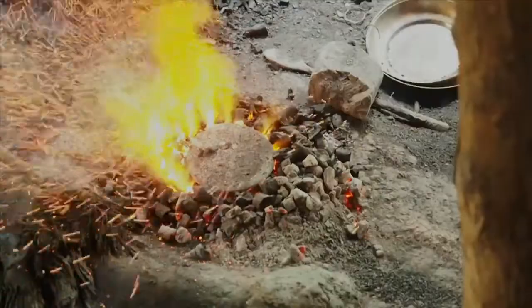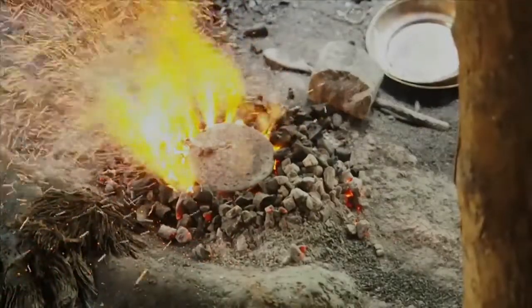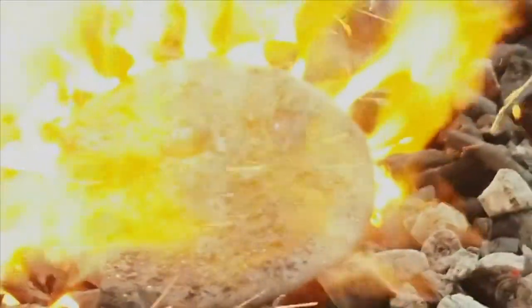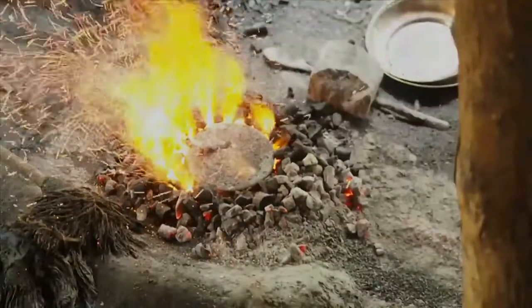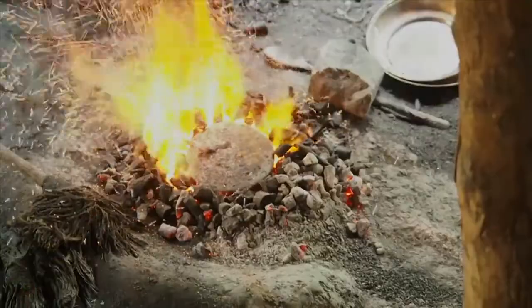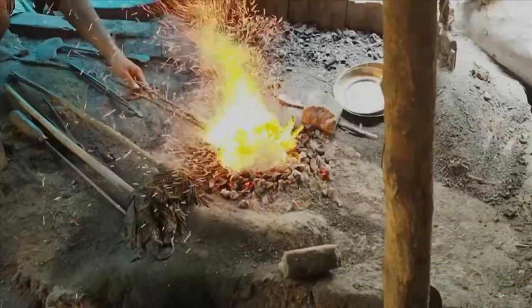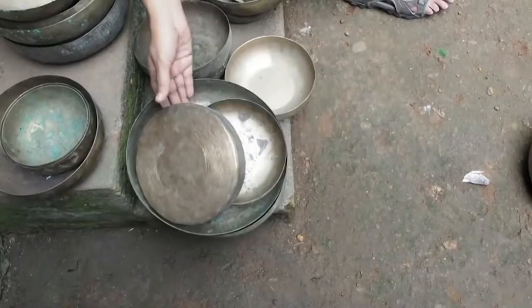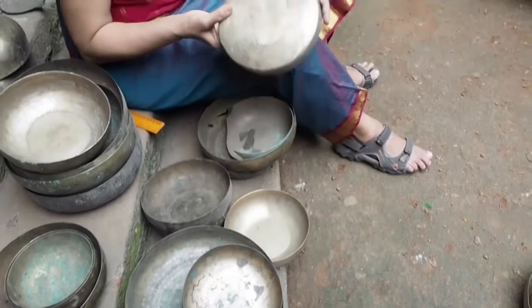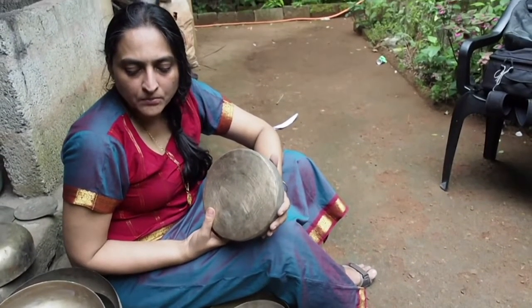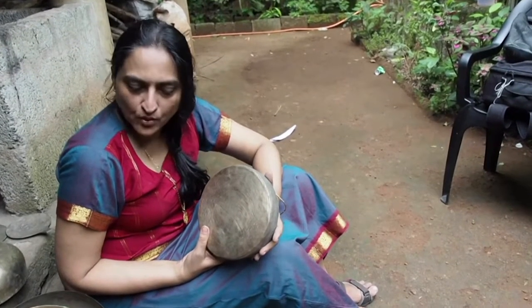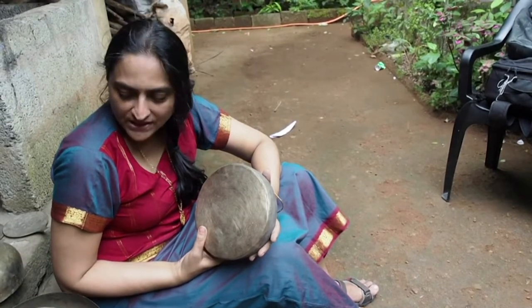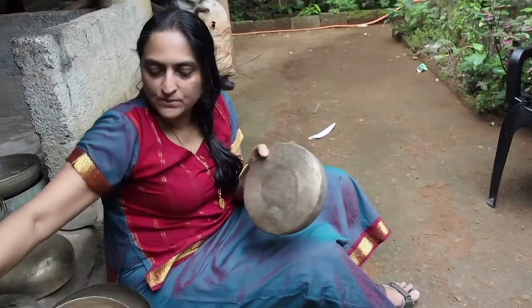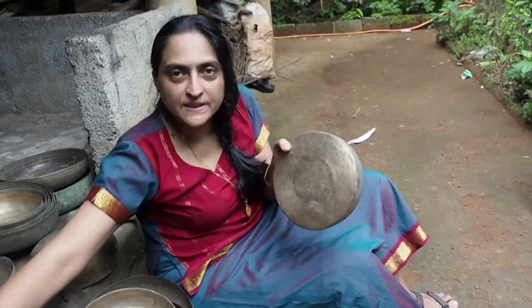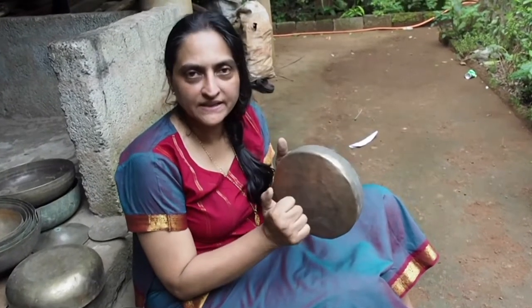The cymbal blank is forged by a process whereby one craftsman holds the blank and two others hammer it alternately, while it is turned consecutively by the man holding it down. Now, this light golden yellow alloy of high-tin beta bronze, made of bronze of 23% tin, which has been hot forged at around 600 to 700 degrees centigrade and then quenched, has one property in common, which is why it was used not only for gongs but also for vessels and cymbals, musical instruments: it has this property of tonality.